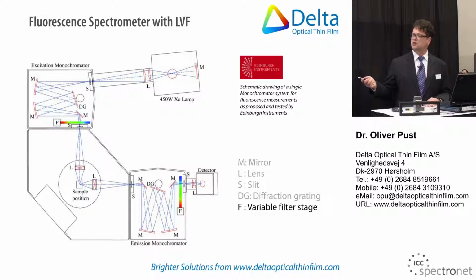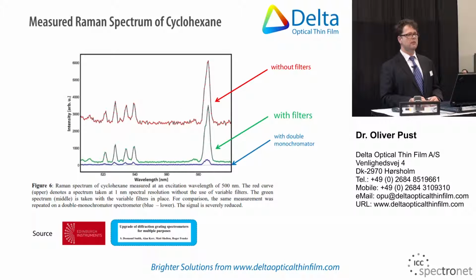Here the red curve shows the results of Raman measurements of cyclohexane without the filters. That means one monochromator, one grating. You see the signal peaks and you see the noise floor. And if now the noise floor is too high, the signal to noise ratio is not good enough, you can use a double monochromator, which makes your spectrometer very bulky, expensive and very sensitive. And then you get the blue curve, which gives you a nice clean noise floor. But of course your sensitivity, your signal strength has dropped quite a lot because of the second monochromator stage.